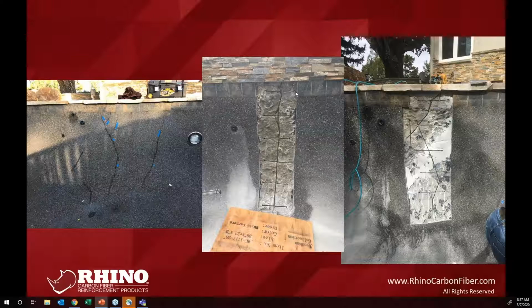And as you can see, there's one of them actually slotted in here and installed, slightly subsurface. He's got it slightly recessed, and then he filled it with carbon fiber and will top it with the exposed epoxy. Then we chase the crack with epoxy and you're done. In his case, we arrested it. We stopped the crack here, and here it stops. We actually went a little bit further than the crack so that it would arrest it in case the crack moved slightly. When it does, it'll go down and there's another crack lock, it stops.